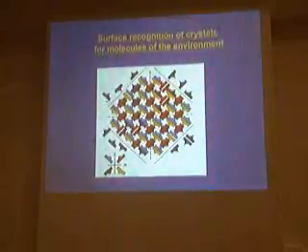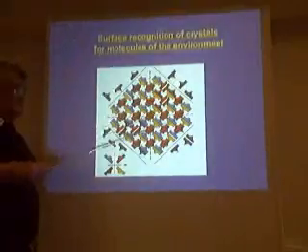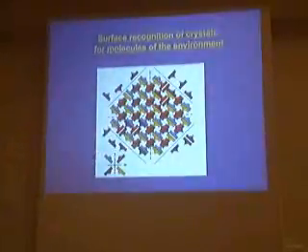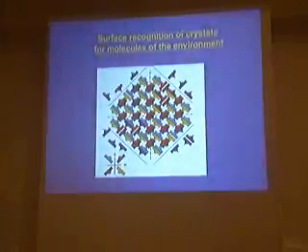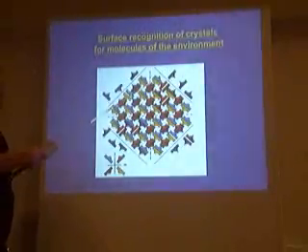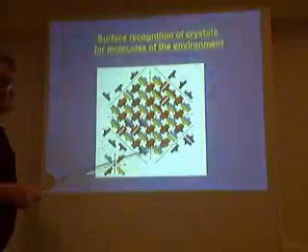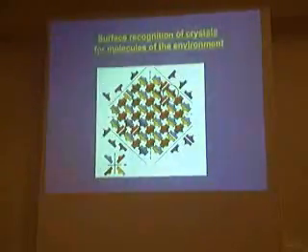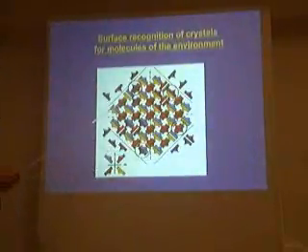But the problem is the following. If you go to the mechanism of the formation of a mixed crystal, the molecule first has to be attached to the surface before being occluded by overgrowth on this particular surface of the crystal. Therefore, if you take a crystal which is centrosymmetric and grow it with a guest molecule, in principle you should get a mixture of sectors, where, because of the kinetically controlled process, each sector should have a different composition. Because if the surface recognizes this molecule here, it should be attached only to the azure, or it could be attached here to the azure group. Here they will be attached to the green, here to the yellow, and here to the red.